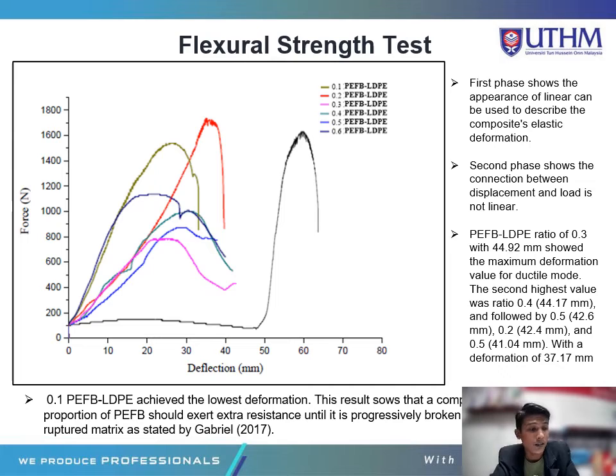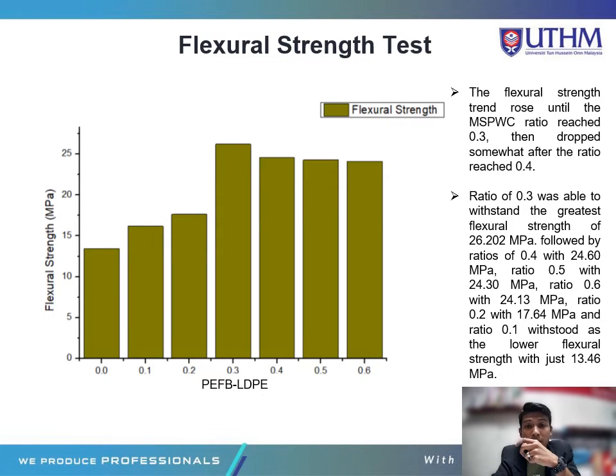This result shows the composite having a large proportion of PEFB should exert extra resistance until it is progressively broken or pushed out of the fully ruptured matrix, as stated by Gabriel's study 2017. For the flexural strength test, the strength rose until the PEFB ratio reached 0.3, then dropped somewhat after the ratio reached 0.4. Ratio 0.3 was able to withstand the greatest flexural strength of 26.202 MPa, followed by ratio 0.4 with 24.6 MPa, ratio 0.5 with 24.3 MPa, and ratio 0.6 with 24.13 MPa. Ratio 0.2 had 17.64 MPa.